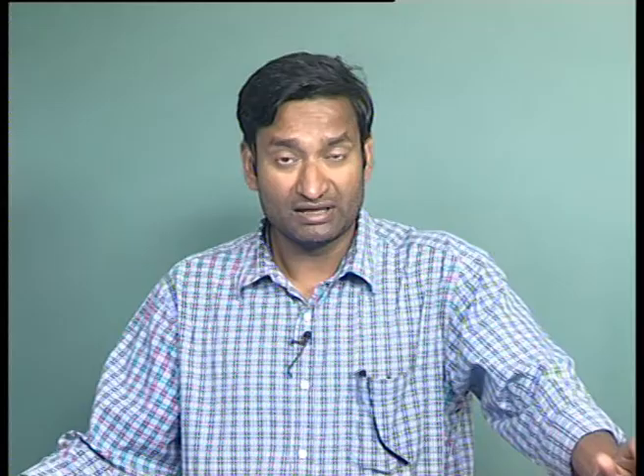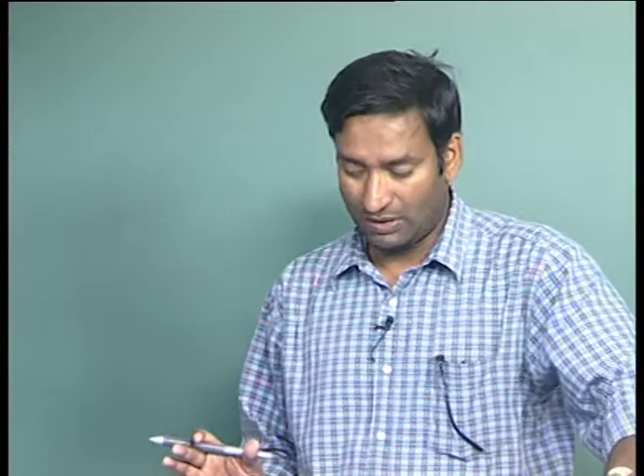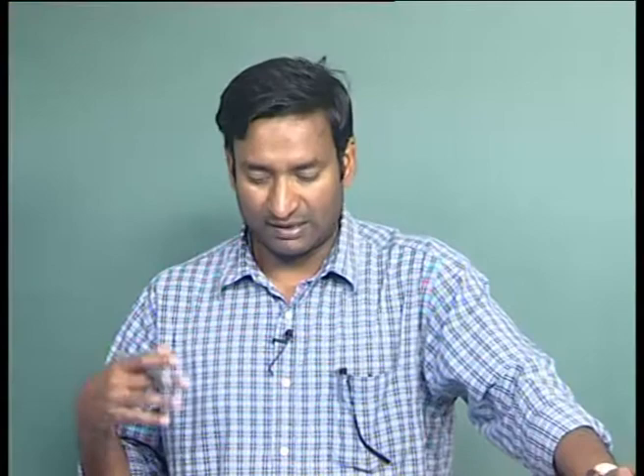We also looked at an analytical treatment for domain wall width, finding that this width is related to the polarization of the crystal as well as the surface energy of the domain wall itself. Larger domain wall energy means larger domains, because more energy is required to create many domains. But larger polarization leads to smaller domains, because larger polarization means a larger depolarizing field and more driving force toward forming domains. It is the competition between these two energies that forces the domains to achieve an equilibrium configuration of a particular size.